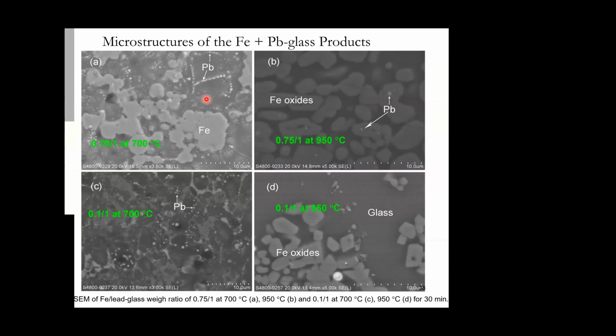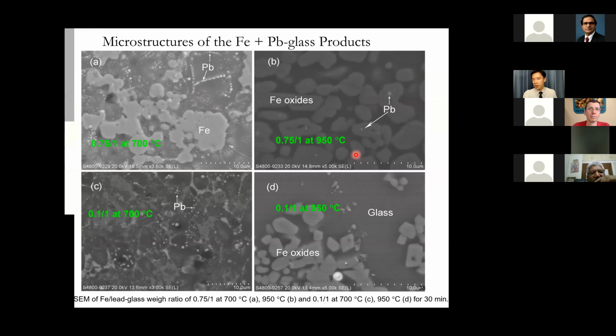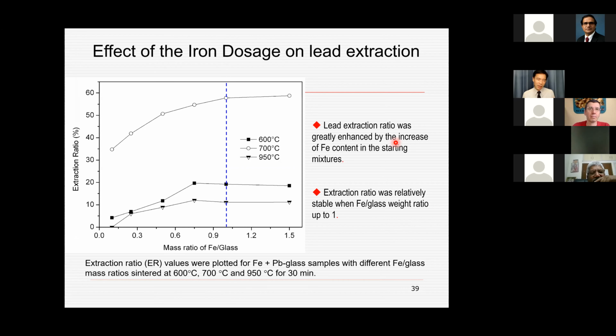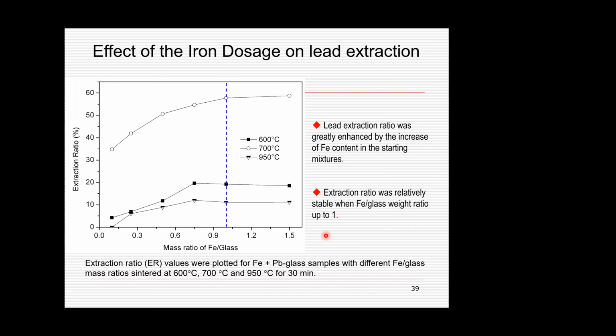Like this 700 degrees Celsius under SEM, you can see the metallic lead coming out very easily. But when you think, okay, let me boost up the temperature a bit higher, maybe I can have a better result, then you were wrong. Because say at 950 degrees Celsius, you actually don't see the metallic lead at all. It kind of dissolves and then goes back to the matrix. So again, the tool that we have helps us to optimize the operation, tell the engineer what will be the best recipe and process that you should design.